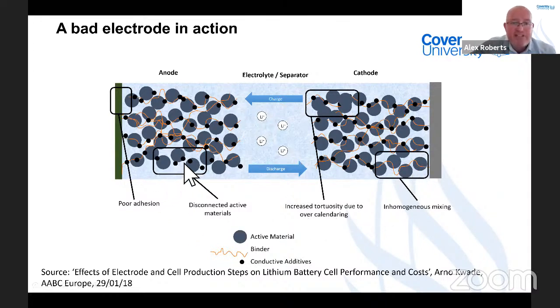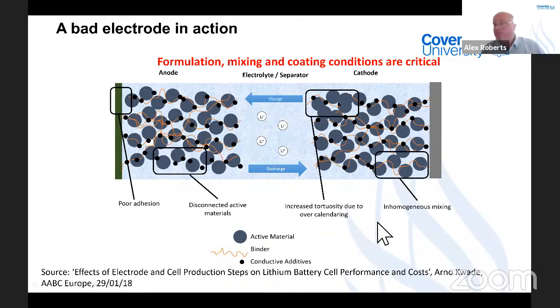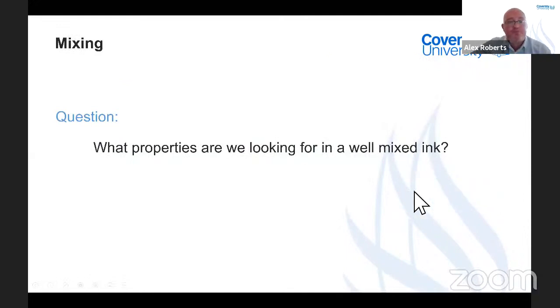So we're going to lose some of this active material. We have disconnected materials that may be sitting there without the binder. We're not going to see these in capacity. We can have poor adhesion to a current collector and it can wind off. There are so many things that can go wrong inside an electrode if everything is not just right. So the formulation, mixing and coating conditions are absolutely critical.